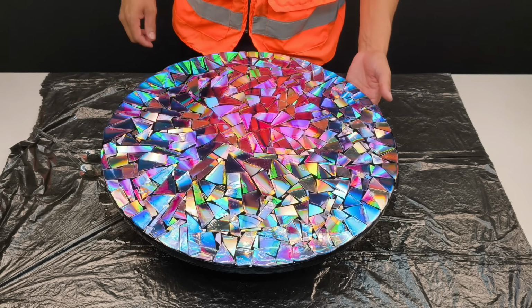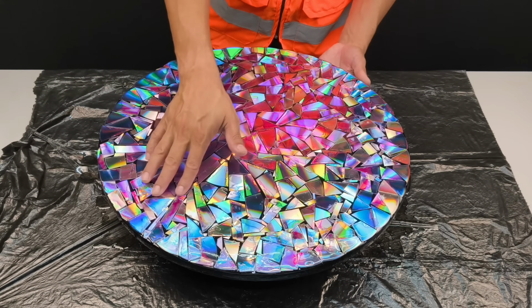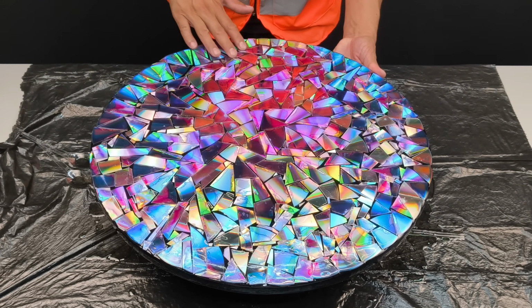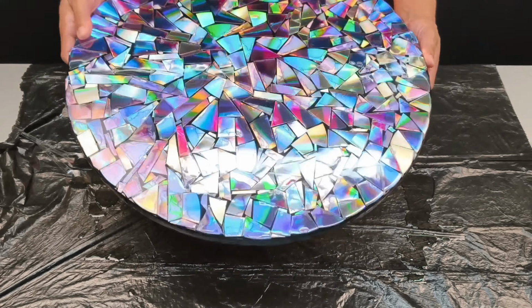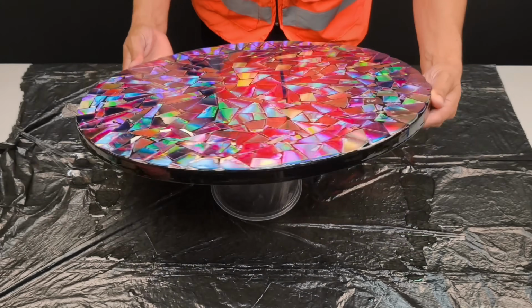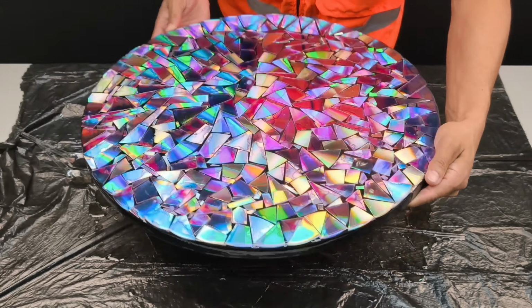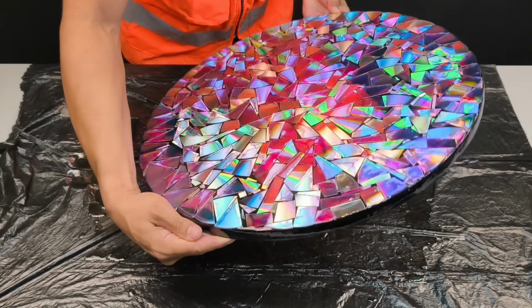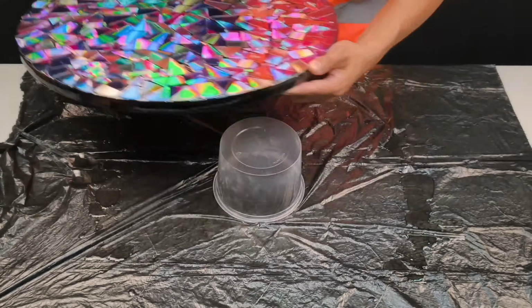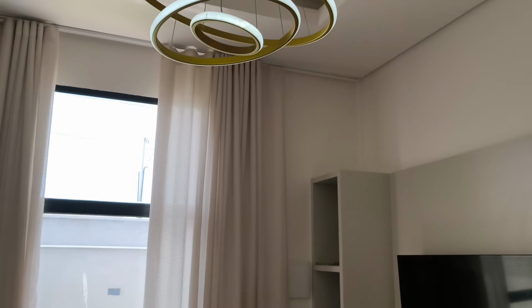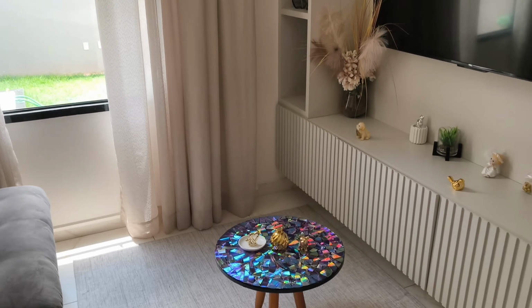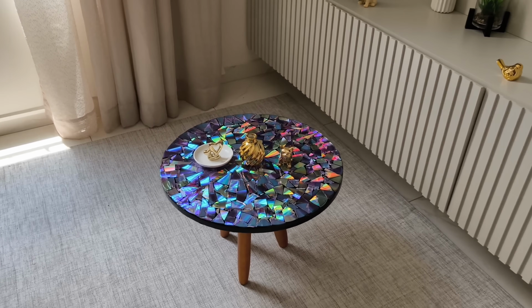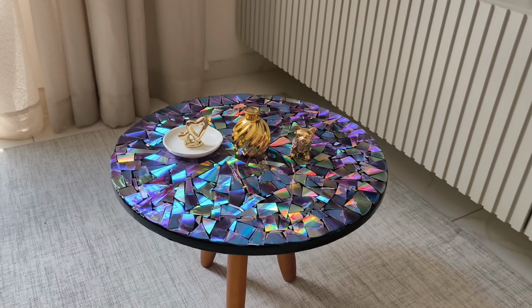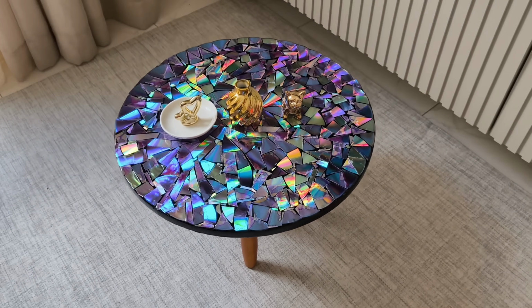After 24 hours of curing, the resin is fully dry, revealing a high-gloss surface with a refined finish. The piece is complete, with a sophisticated look and ready for use. The result stands out not only for its appearance, but also for its function, making it a true standout piece. Here is the final result of the entire process, executed with precision and patience at every stage.